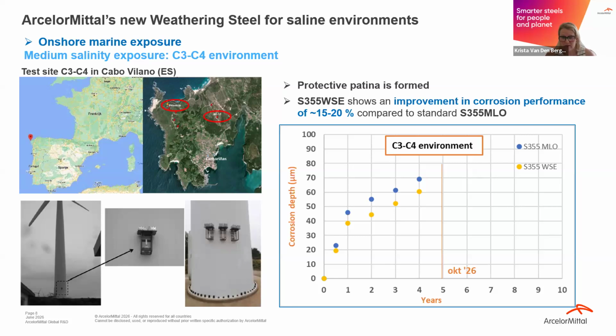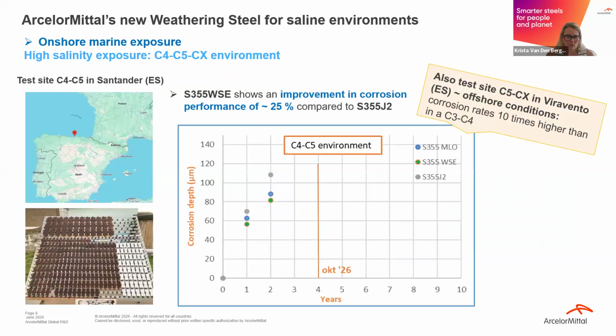So this is a benefit where we really think that this trend, the decrease of the corrosion rate as a function of time, will further progress. So if we move even to higher chloride loads, we have a C4, C5 exposure, also in the north of Spain. And here we see that we also have a benefit of 25% compared to S355J2. And here we only have an exposure of 2 years, but we think the same trend will continue.